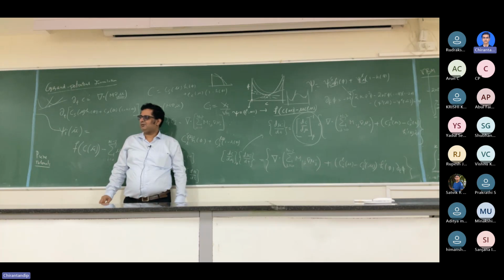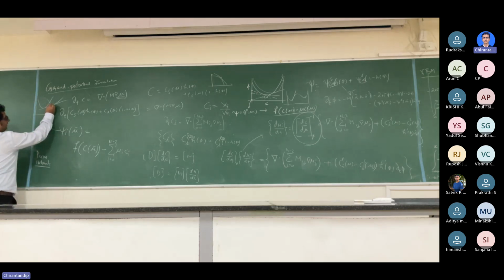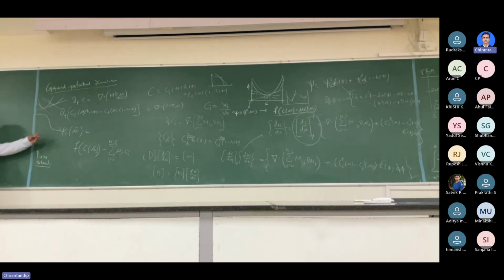If I adapt the system towards a non-equilibrium state, I will change the composition of the liquid, so the free energy of the liquid has to be here. Then your chemical potential cannot be on this line. If your chemical potential is on this line, whatever you do, it's in equilibrium. If your chemical potential corresponds to the composition here in the liquid, that is what you initialize the system with, you naturally have a driving force.